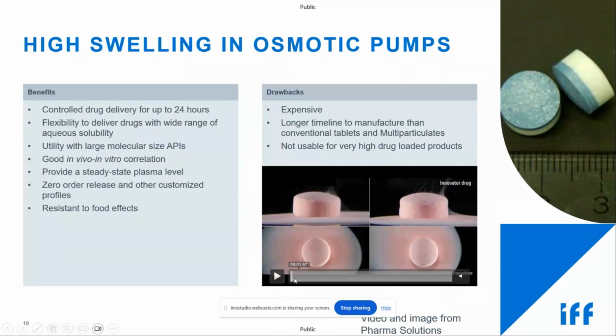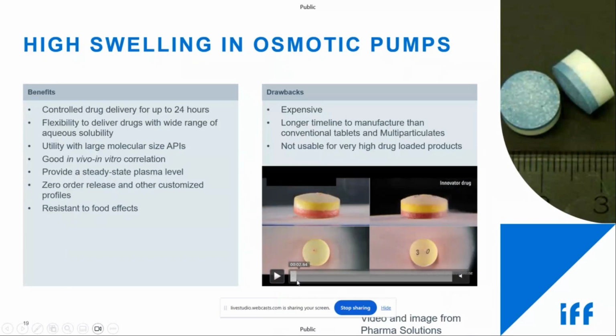So this is put into water. You can see the aesthetic coating starts to come off. That pink goes away, and the cellulose acetate coating is clear. And you can see the two different layers of this osmotic pump. In this case, we have a push layer in red and a drug layer in yellow, and, probably hard to see, there is a drilled hole at the top of this.